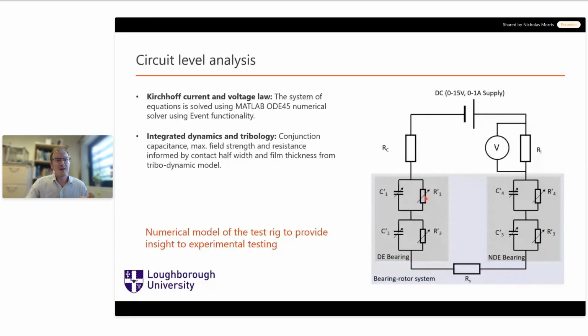The other thing that we include within this resistance is we switch between a resistance when we're below the breakdown voltage of the contact, which is comparatively high based on the conductivity of the fluids. And then if the breakdown voltage is exceeded, we move to the resistance of the arc, which is much, much lower. And as a result, we'll have a significant discharge of current across the contact. So through the use of the experiment and the model, we can understand how different parameters relate to each other and cause the damage that we see from the bearings that we examine at the end of the test.